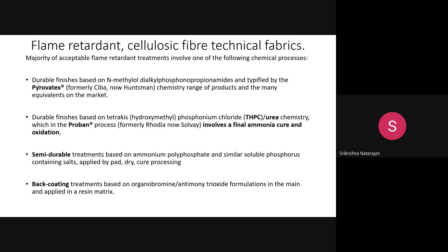These two are for durable finishes. For semi-durable finish, ammonium polyphosphate and other metal salts can be used. If you want to provide flame retardant coating on only one side — for example for a carpet where only the surface needs it — that is also possible using a bromine compound along with antimony trioxide, which is a metal oxide. Antimony oxide does not work alone but works when mixed with bromine, chlorine, or phosphorus.